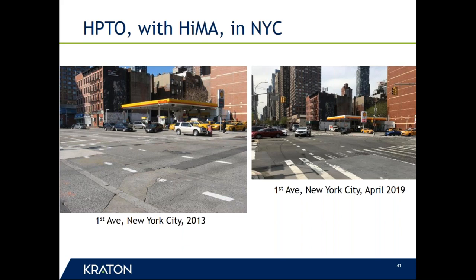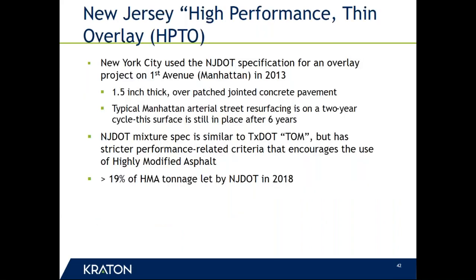They came in and milled that surface down to get a uniform texture and so on. They applied a very heavy tack coat with 76-22, and then they resurfaced that with 1.5 inches of asphalt in 2013. 2019, it's still there and still performing well. Now, utility companies haven't stopped. They went back in there and they've done some things and done some patching as well, but where they haven't gone in, that surface remains intact and in very good condition, according to the New York City DOT.